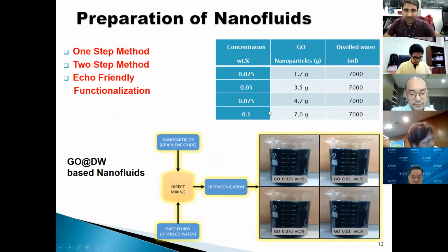My preferred weight percent concentrations are 0.025%, 0.05%, 0.075%, and 0.1%. According to the percentage, the base fluid is distilled water. The minimum is 7 liters, which is the requirement of our experimental setup.